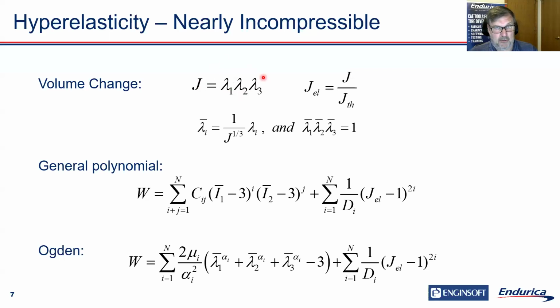and you can convince yourself that lambda 1 times lambda 2 times lambda 3 gives you an indication of the volume in the specimen. Now we want the volume due to the elastic energy, not due to something like thermal expansion or contraction. So we take out the thermal effects and just look at this J elastic to characterize or measure the volume change. Associated with the volume change overall are the extension ratios. And now we're going to define the lambda bars, which are the extension ratios for the volume conserving part of the deformation. They're defined by this expression, so that lambda 1 bar times lambda 2 bar times lambda 3 bar is always equal to 1, and thus the volume is conserved.